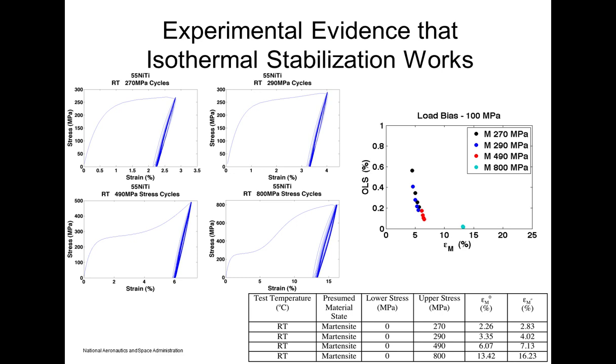we would see that material as a very highly evolving system. In fact, here at Glenn we call it a type 2 evolver, so it's a high evolver, low transient type system. And so in that case, if we were to run a simple tensile dog bone in an isobaric condition where we've loaded it to 100 MPa and then held that 100 MPa and thermally cycled it back and forth between room temperature and 165 C, we would see that system evolve like you saw in previous curves. That system would evolve to on the order of about 14% strain before it reached a level that we would consider it dimensionally stable. Okay, so if we now take a virgin material, virgin tensile specimen, and we know that the level is 14%, but in this case we're going to do some isothermal deformations on that material that wouldn't reach that level of the deformation state.